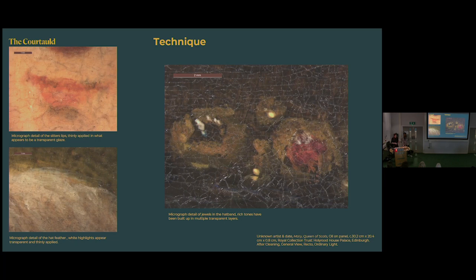We began analysis after the cleaning, looking under the microscope, which revealed that the paint layers have in general been very thinly applied with semi-transparent glazes very rich in binding media applied either directly onto the ground or above more opaque passages of paint, in order to create richer effects with more depth and luminosity.